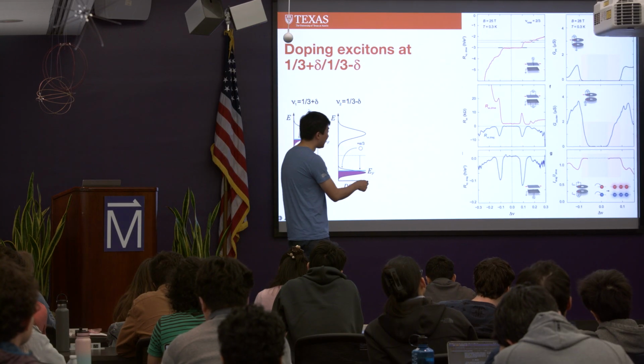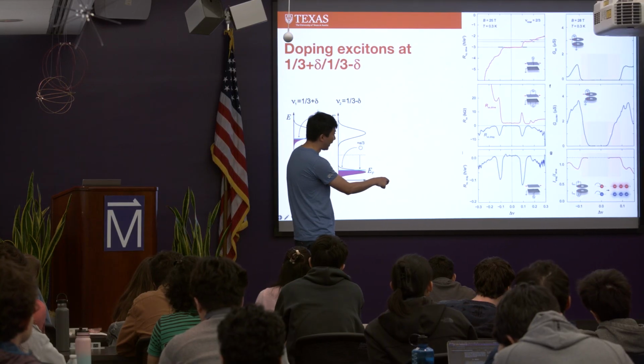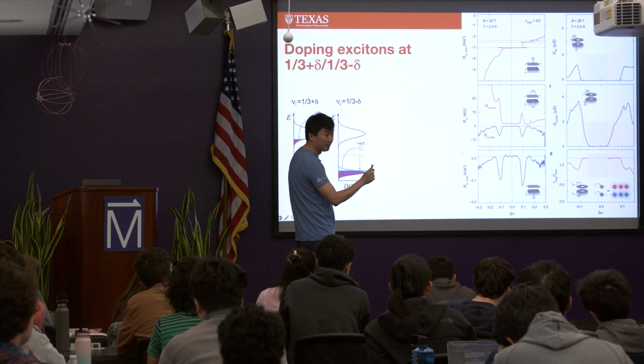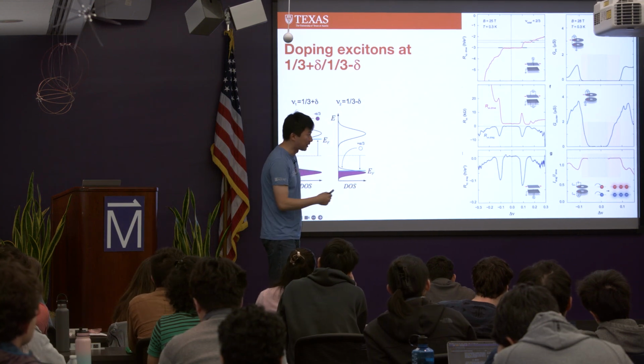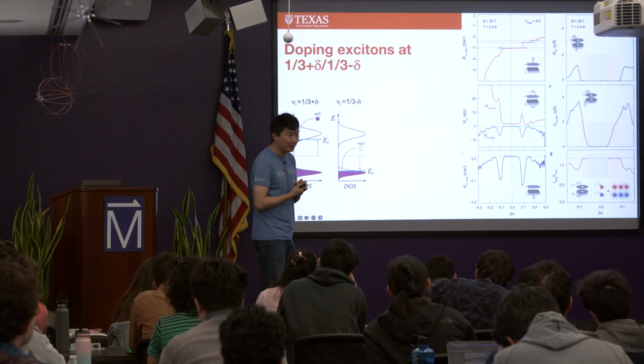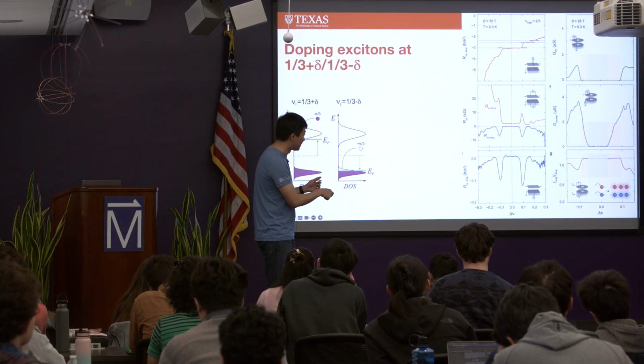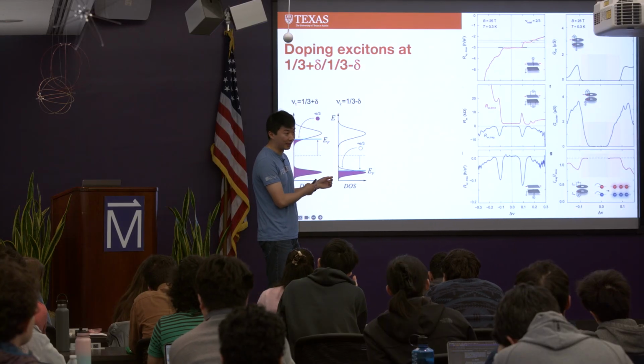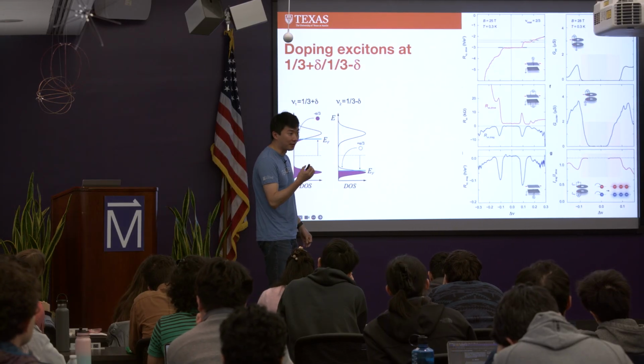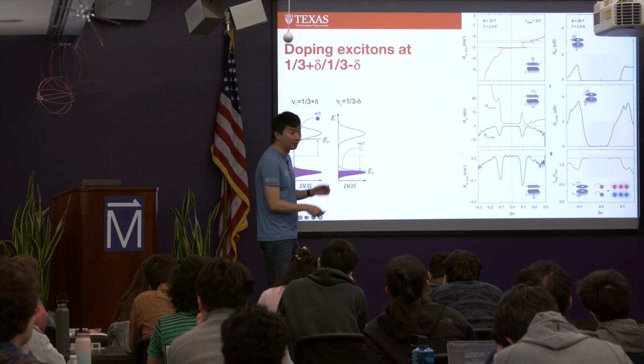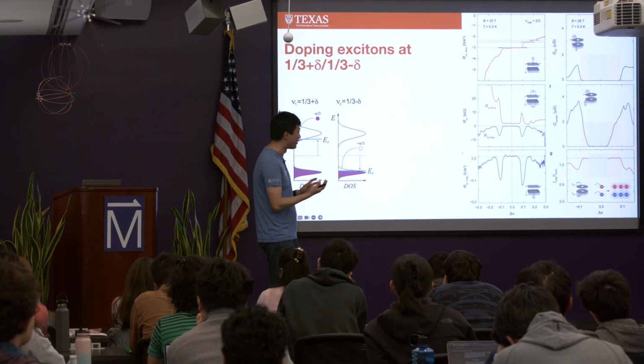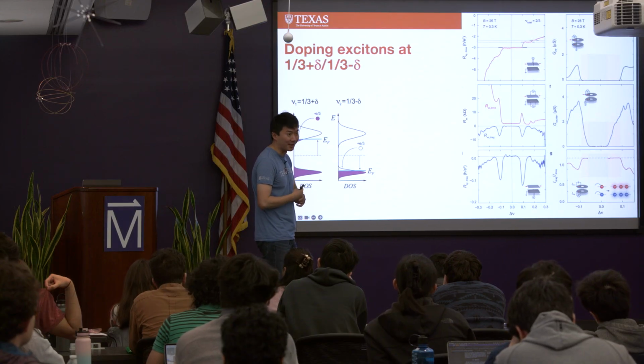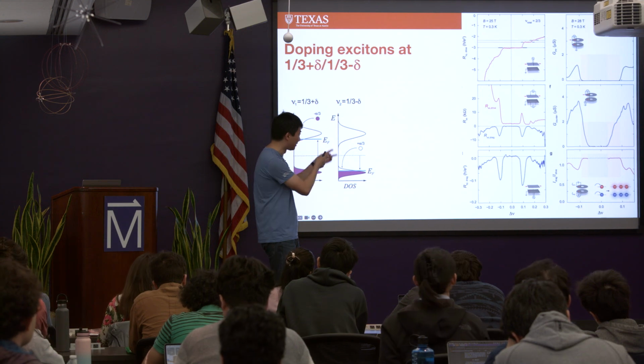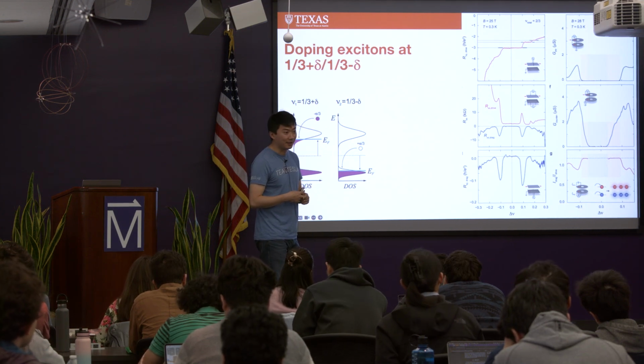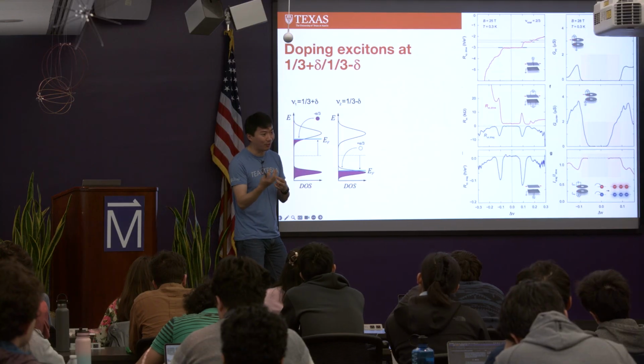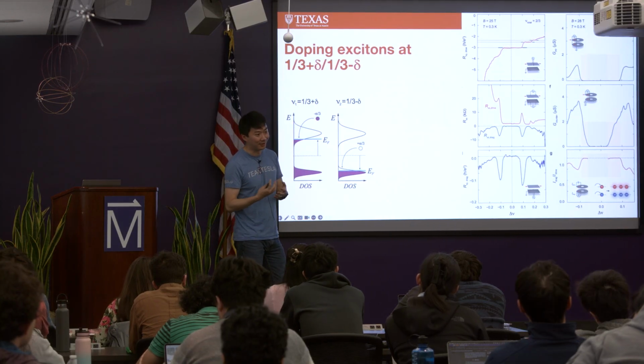Oh, so okay. If you look at the Corbino measurement, when the exciton starts to onset, the charge gap is still very robust. Right. So in this case, this fractional exciton corresponds to an incompressible state. What happens in the Hall bar is that, even though it shows interlayer correlation, this state is not fully developed. So when excitons start to appear, it's a compressible state. That's why it deviates from the plateau. Right. And there is a fundamental difference between Corbino and Hall bar shape that we don't fully understand, although this difference exists for both this quantum Hall bilayer and also monolayer. How the edge and the bulk interact probably is the key, right? The interaction is in a way that's non-trivial and we don't fully understand.